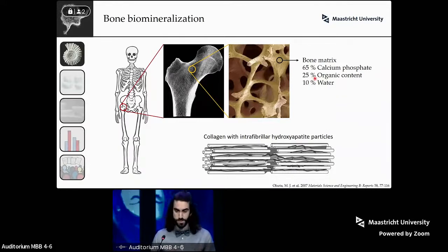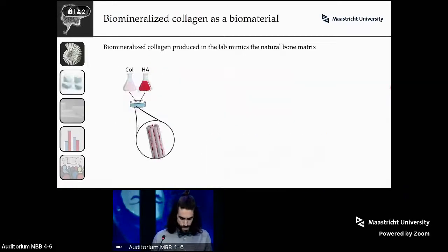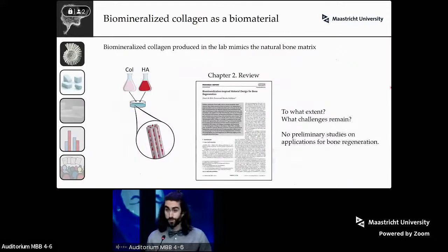Not only the composition is important, but also the structure, and in particular, how the collagen is organized with the mineral components. The mineral particles are embedded inside the collagen fiber, and this is in part a reason for its very strong toughness and other mechanical properties. Now, critically, this structure of embedded mineral particles within the collagen fibers, what we call intrafibrillar mineralization, was able to be reproduced in the lab by an ingenious process. And this was actually the topic of my review chapter.